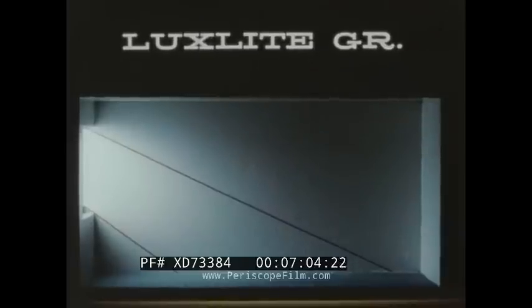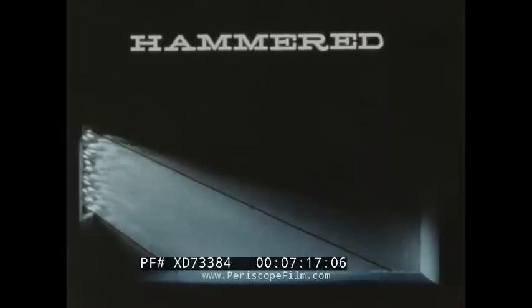This particular sample has been glare reduced on the pattern side. This glass has a light transmittance of some 15% less than the untreated sample, or a total of about 74%. We normally recommend glazing the glare reduced surface toward the interior of the building so that it will be less susceptible to dirt and even more accessible for cleaning.